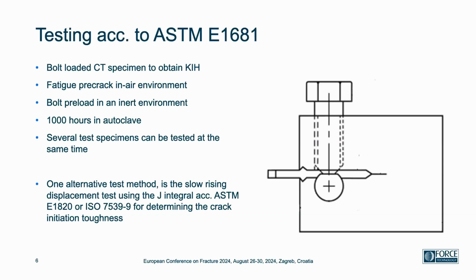The test procedure, just described in short, is that a fatigue pre-crack is conducted in an in-air environment. The specimen is then inserted into a glove box, which is an inert environment where there are strict requirements on the levels of oxygen and H2O. And the bolt is preloaded with a clip gauge to know what the crack mouth opening displacement is. The specimen, or the several specimens, are then inserted into the autoclave. The standard specifies, or the KD-10 in the ASME BPVC Section VIII defines, 1,000 hours for carbon steel. And one of the pros of this test method is that several test specimens can be tested at the same time.